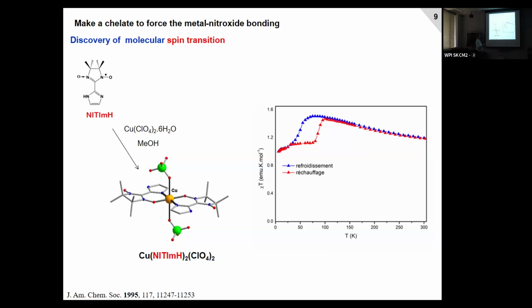And so when you cool, this here is the product, I should explain before. This is the product of magnetic susceptibility with temperature. Here is the temperature. When the product of the magnetic susceptibility with temperature increases when you cool, this means you have ferromagnetic interactions which are dominant.